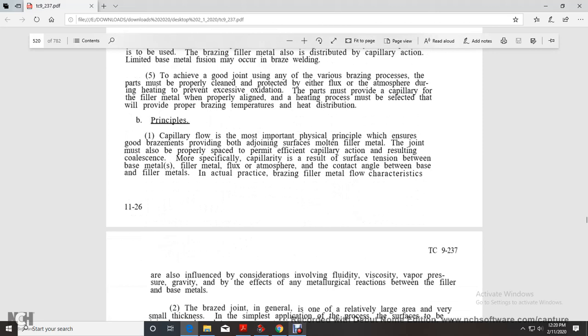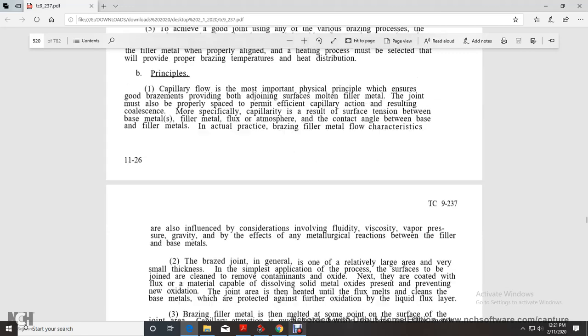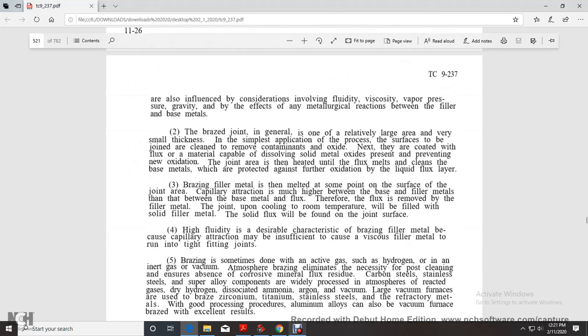Capillary flow is the most important principle to ensure a good brazement. It requires wetting of the joining surfaces by the molten filler metal, and the joint must also be properly spaced to permit efficient and effective capillary action. More specifically, capillary action is the result of the surface tension between the base metal, the filler metal, and the flux or atmosphere, with the contact angle between the base and filler metals. In practice, brazing filler metal flow is also influenced by considerations involving fluidity, viscosity, vapor pressure, gravity, and the effects of metallurgical reaction between the filler metal and the base metal.